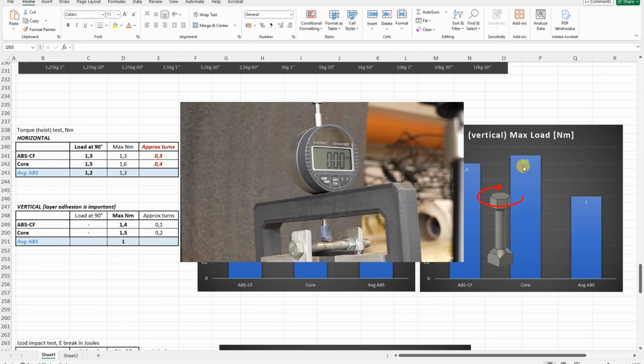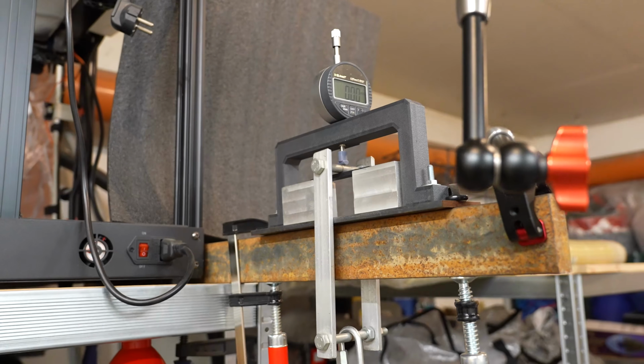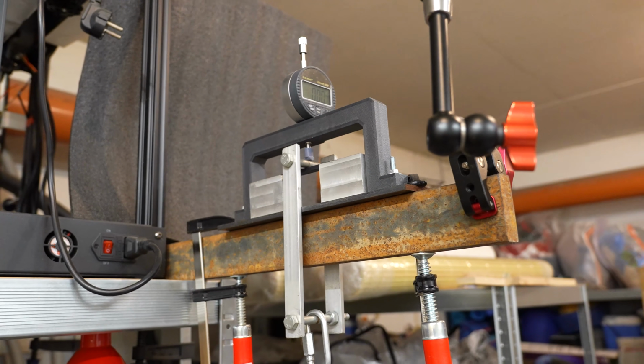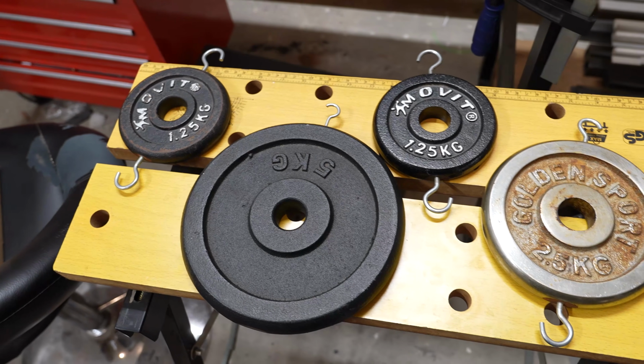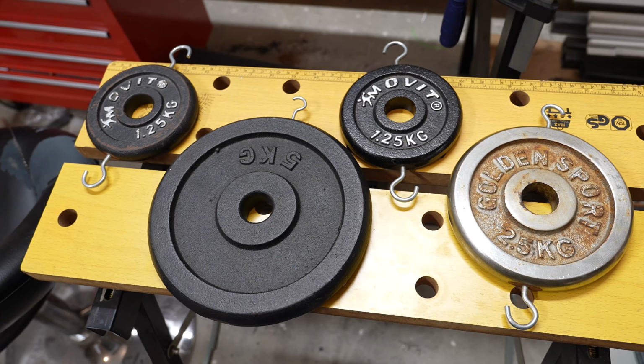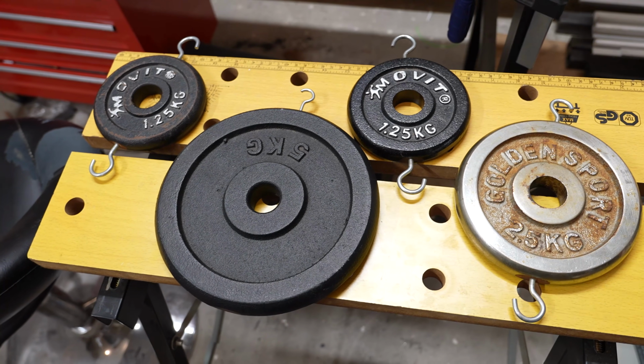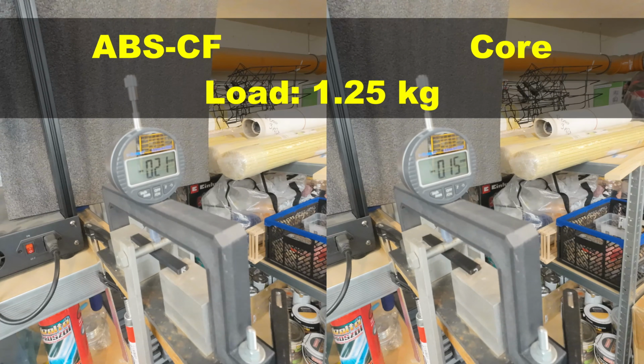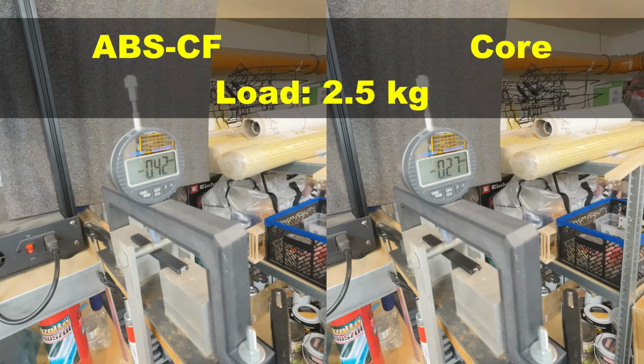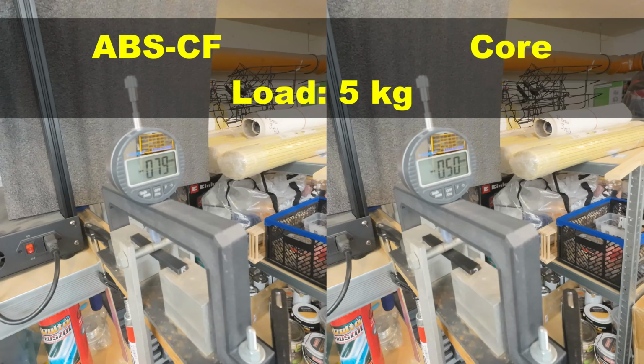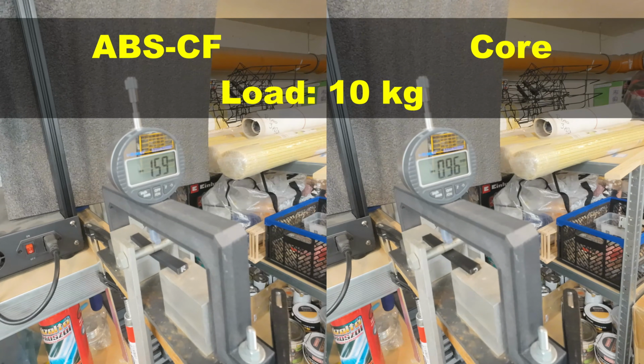And now 3-point bending test. Distance between supports is 50 mm, and these loads will be placed one by one, and I'm measuring the deformation after 30 and 60 seconds. Side by side two materials, deformation under 1.25 kg, under 2.5 kg, under 5 kg, still no additional deformation during the time, and only here under 10 kg I can see some additional deformations.